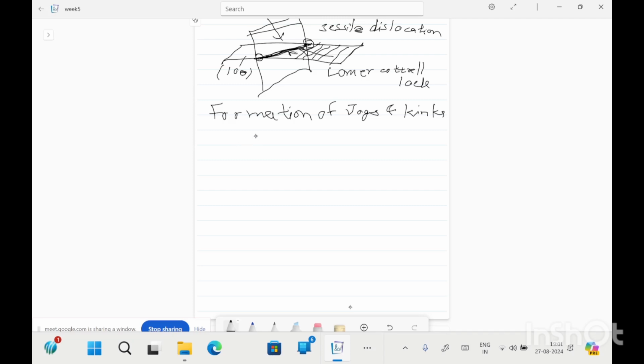So jogs are formed as the dislocation line interrupts. If this is an edge dislocation, and its Burgers vector is in this direction, and the line vector is in this direction, so it breaks along this plane. The Burgers vector is out of plane. So a jog is a step formed in the dislocation line out of the original slip plane. If this step is out of the slip plane, it is called a jog, and if it is in the plane, then it is known as a kink.